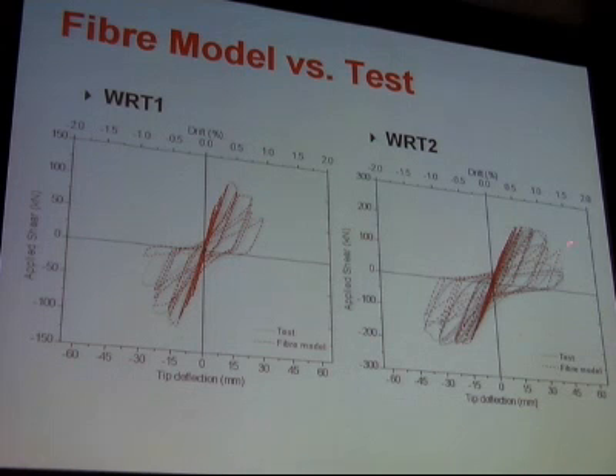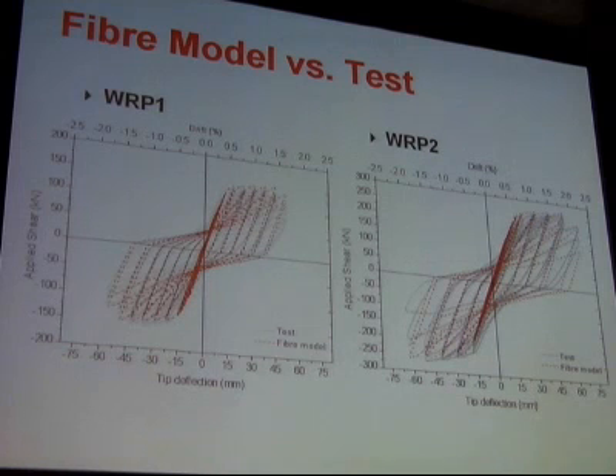the experimental results. And then for the more severe retrofit, where we're using fiber-reinforced self-consolidating concrete as well as the fiber wrap, we see much improved response and the predictions of the fiber model versus the experimental results.